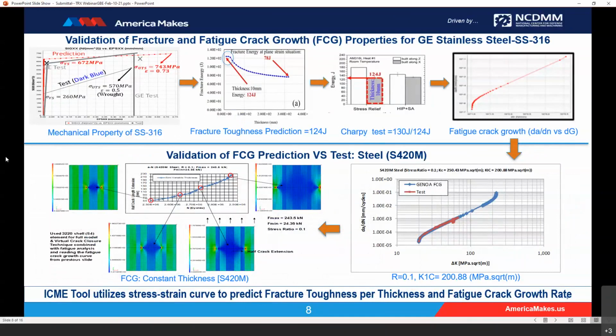Validation of fracture and fatigue crack growth properties for GE stainless steel. This slide presents the fracture property prediction of the GE stainless steel based on the post-build heat treatment. The ICME methodology for prediction of fracture toughness per thickness and fatigue crack growth is ultimately derived from stress-strain curves. So on the left, you can see the stress-strain curve for that particular GE steel. And now we're going to use that fracture toughness per thickness methodology to predict fracture toughness and ultimately predict fatigue crack growth rate.